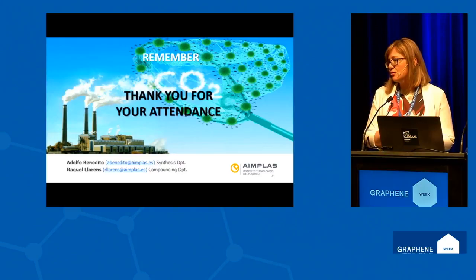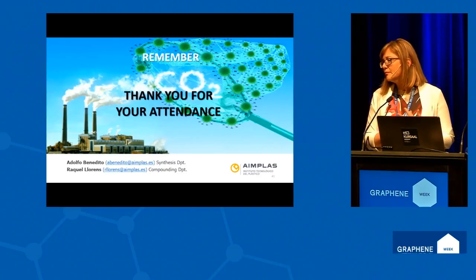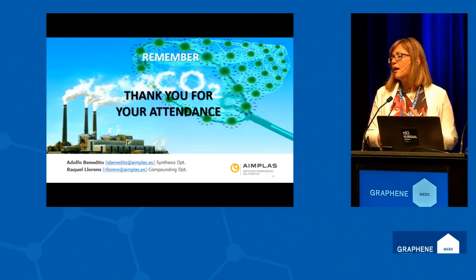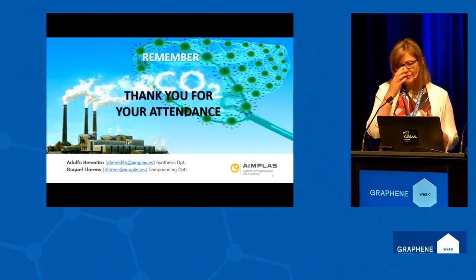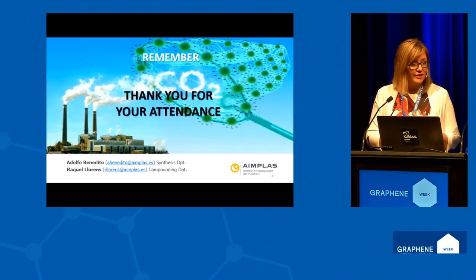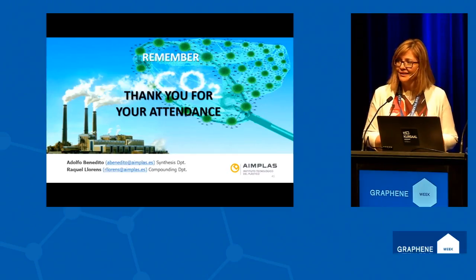So if I understand you correctly, the highest capacity is not when you use graphene on its own, it's when you mix graphene with something else. Exactly. It's the combination. Did you measure the surface area of the final material in square meters per gram? I imagine yes. I don't have this data here, but yes, because we are characterizing the materials. If you need this data, I can check and send it to you.